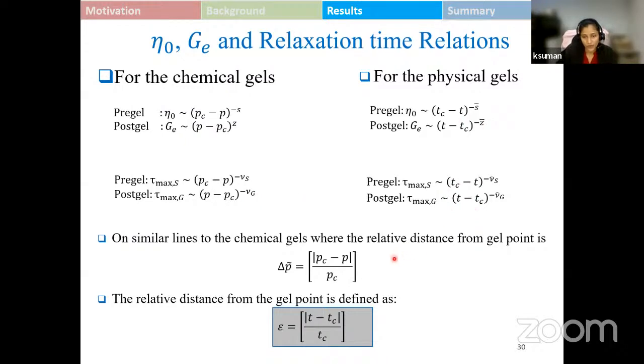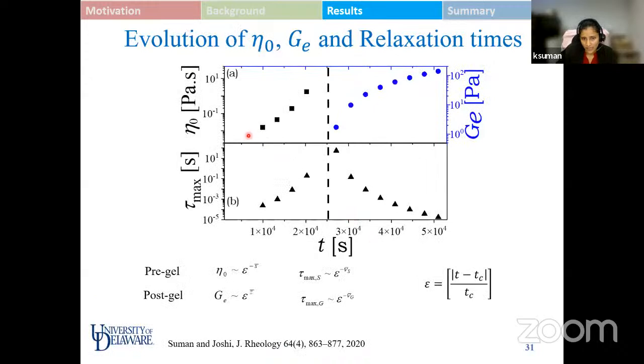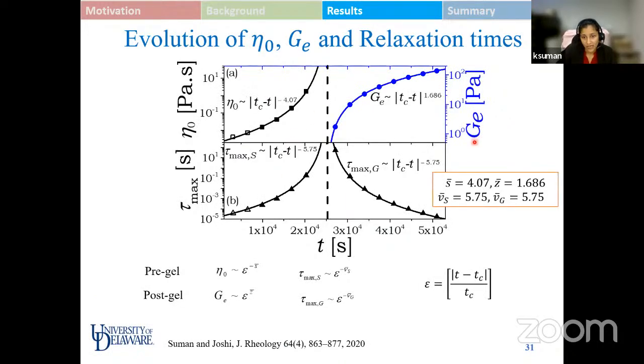And with this, we try to fit the scaling laws to the parameters which we quantified from the experiments, and we can see that these power laws fit very nicely to the experimental data. We quantified the different power law exponents with which the zero shear viscosity, the equilibrium modulus, and the longest relaxation time scale in the pre-gel and the post-gel region evolve. So all of these are very nice power law scaling laws shown over here.